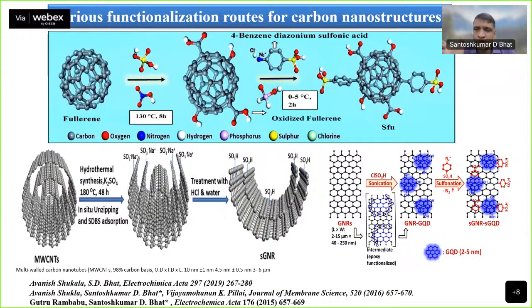So we have worked on those issues recently, and we have been able to functionalize these carbon nanostructures, because much of the research focus is on functionalizing carbon nanostructures, because anything over the threshold limit gives a certain electrical conductivity feature in carbon nanomaterials. To overcome these features, we need to functionalize these materials to keep this in balance. So we have done a sulfanilic acid diazotization route. We have also done unzipping of multi-walled carbon nanotube and in situ adsorbing sodium dodecyl sulfate into that to induce the sulfonic acid groups onto these carbon nanomaterials. And then when we unzip the carbon nanotubes, we use a super acid, chlorosulfonic acid, and then you diazotize again, and then you have beautiful graphene quantum dots of 2 to 5 nanometer on the surface of graphene nanoribbons, so that it forms an overall composite.